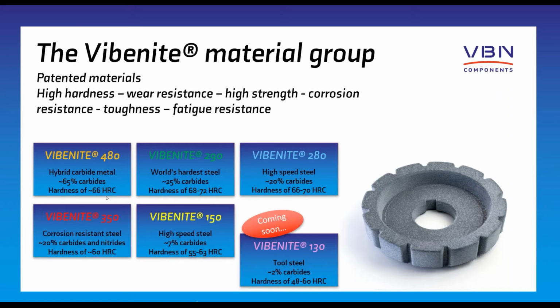This is why we call it the hybrid carbide metal, because hybrid is from the best of the high-speed steel material, which is the toughness, and then we take the best from the cemented carbide material, which is the hot hardness. And this is why you call it hybrid. And here you have an extreme amount of carbides and a hardness range of 66 Rockwell approximately. These are the alloys we have, and all these are patented.